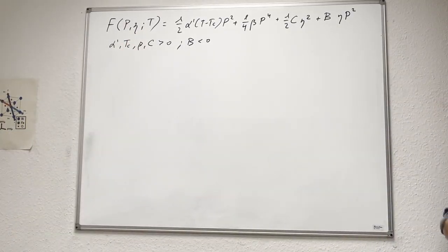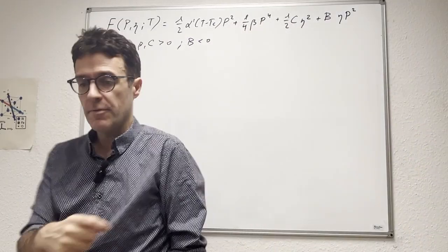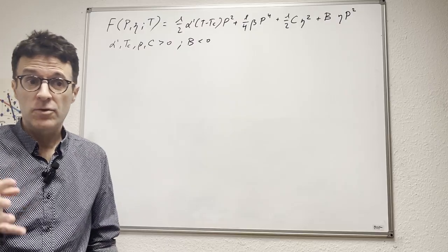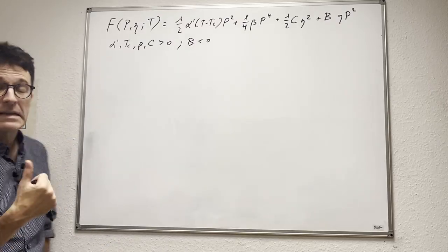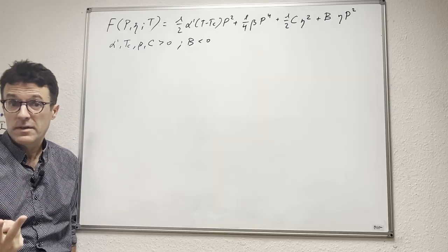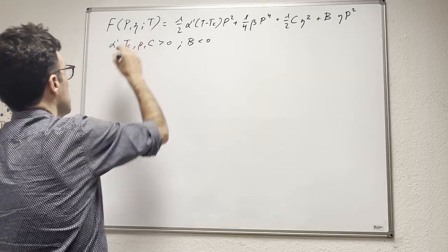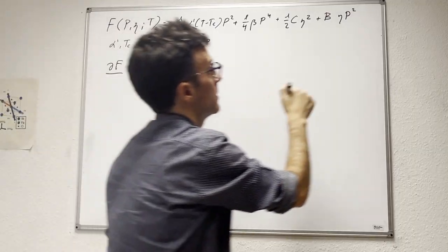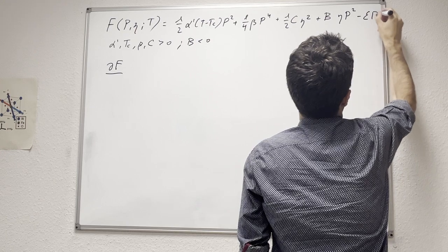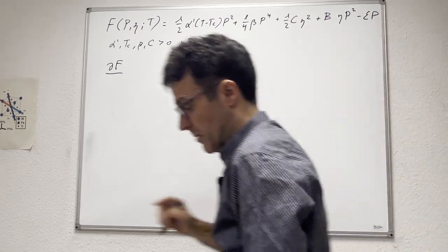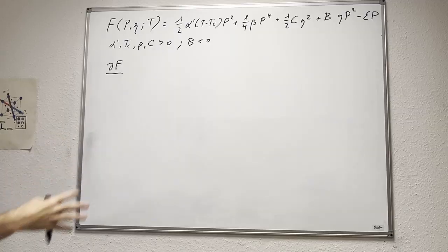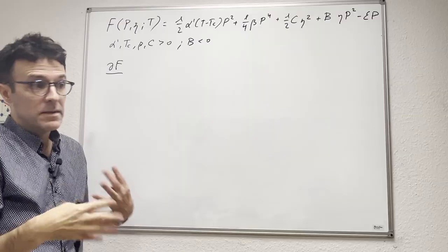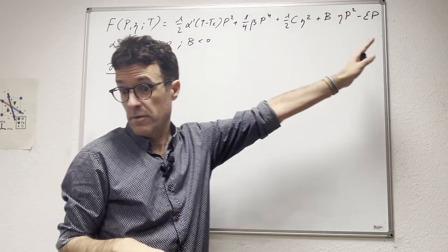And so, if it is a variable, it means that when we think about the equilibrium state of the system, the equilibrium state has to be a minimum not only for the polarization, but also for the strain. Okay? And instead of having a single equation of state, we are going to have two equations of state. Simple enough to write them down. So essentially, exactly as before. Oh, by the way, here, let me put a term that shows the coupling between polarization and electric field. We could add trivially a term that couples the strain to the external stress, but in this lecture we are only going to operate with an external electric field.